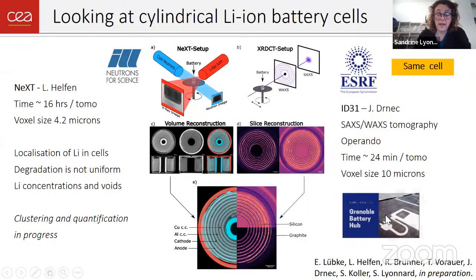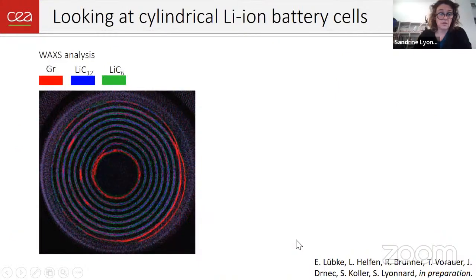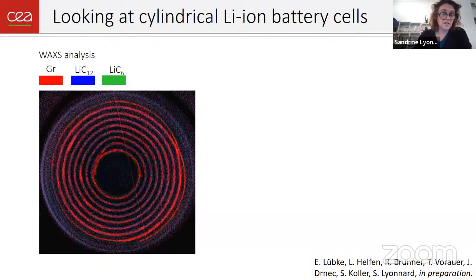And by applying, again, an operando experiment going back on ID31, which is the high energy beamline, where you can do SAXS-WAXS tomography, we can complement this data, and we get SAXS and WAXS data, which tell you the status of lithiation of both silicon and graphite. And you see on this movie, this is a real-time lithiation on the graphite, focusing on the graphite phase. I don't want to comment on this in detail, just you can really see that there are clearly some defects.